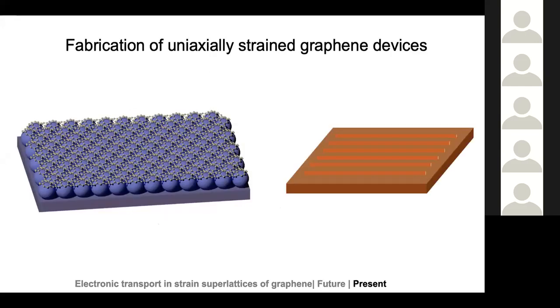So I'll talk a bit now about the present and what I'm fabricating, which is very interesting and sometimes very frustrating. Right now we're trying to study uniaxial strain effects on graphene. If you consider the previous diagram of graphene on nanospheres, graphene was biaxially strained in these devices. If you want a 1D equivalent of such a system, you probably need to consider a set of parallel deformations. Let's call them parallel ridges because that's what they look like. So essentially a set of parallel lines on your substrate. This is not to scale, but when you transfer graphene on top of this, the graphene